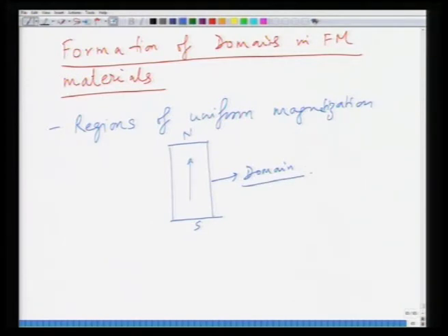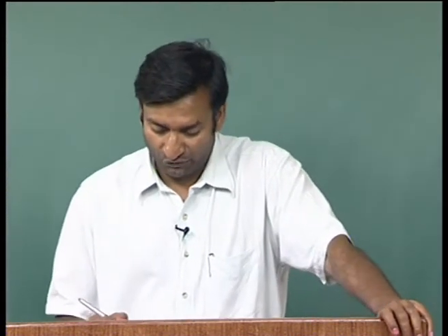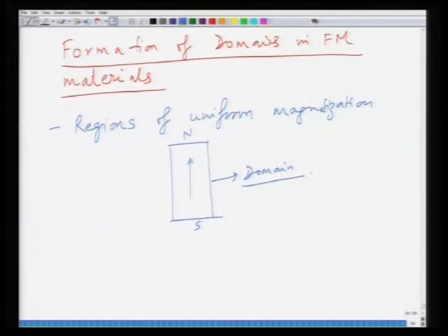Again, refer back to ferroelectric material, although the reasons here are different, it is again energetics. Now, in this monodomain state, Hund's rule allows the spins to be aligned in one direction, and all these atomic spins are aligned in one direction. They of course obey Pauli's exclusion rule, but there is a term called exchange energy, and this exchange energy, without violating Pauli's exclusion rule, allows all these spins in one direction, called the spin up direction.